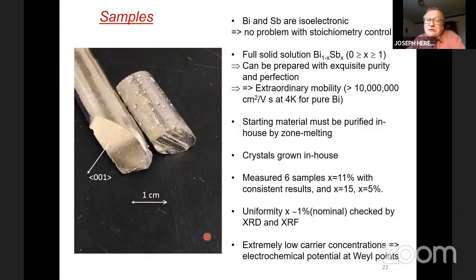by lowering the temperature. Very unlike the situation in bismuth selenide, where it's not antimony but selenium. Any excess atom of selenium would give you an excess electron. Any atom that's missing would give you a hole, and your chemical potential would fluctuate all over your sample. Not so in the bismuth antimony system. The full solid solutions can be prepared with exquisite purity if one is careful.